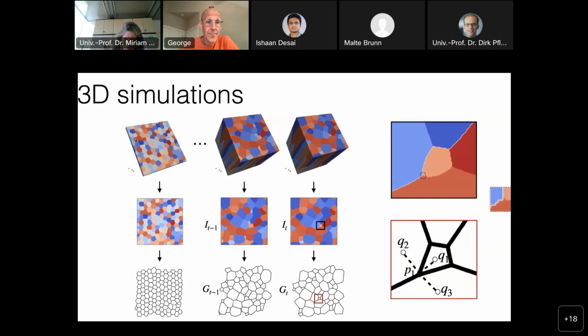Essentially, we're going to take this microstructure, and at different time snapshots, we're going to look at the cross-section. We're just going to take the top surface, similar to what we did in the 2D. From these volumetric calculations, we're going to extract an image at different times that captures the grain shape at this cross-section, and we're going to convert this image to a graph with vertices and edges. We're going to endow every edge and every node in the graph with features, and this will be the input to the network. Given the graph and the vertices, the network will propagate the features to the next time.